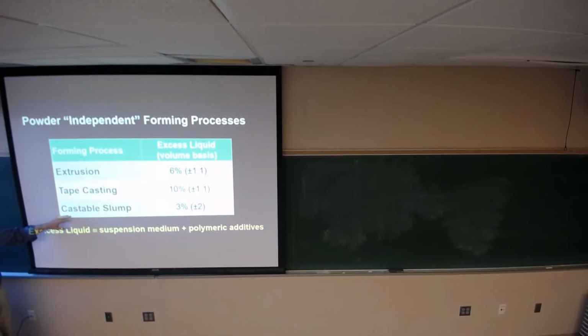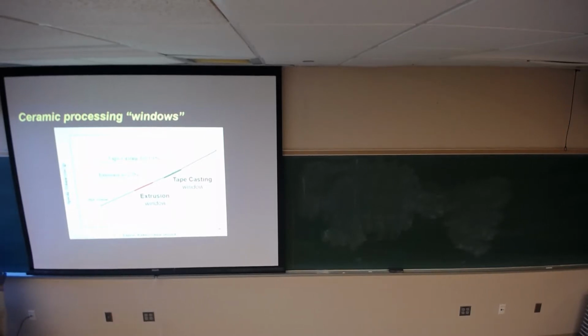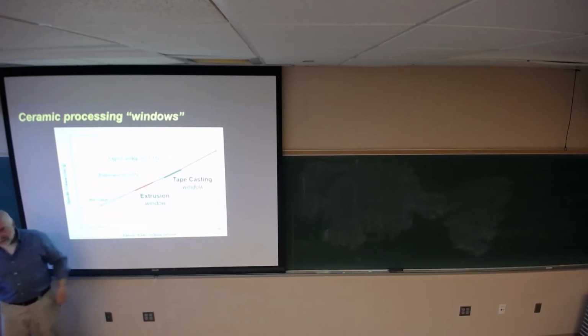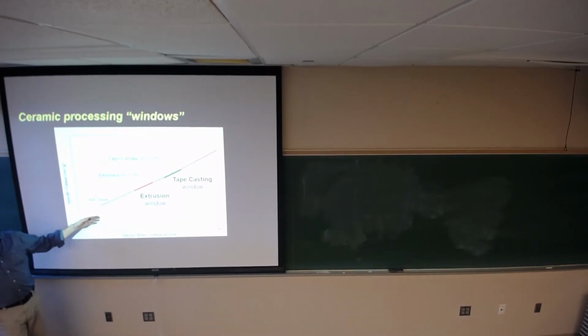Castable slump, this is essentially like vibratory casting or cements. You only need 3% excess liquid in the system to get flow, which is arguably dilating typically in these systems, but that's what you need. You need a little bit of excess liquid to provide room for particles to move around. Okay? It looks like this. I don't have castable slump on here, but here's my extrusion window and my tape casting window. It's my contention that that 1.2% variability in that window has to do with difficulties in measuring pore saturation. Right? So if I'm off of my pore saturation, I'm going to be off of my window for extrusion.